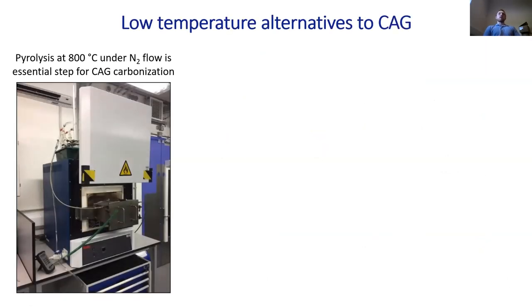The main drawback of the carbon aerogel fabrication route, which is still considered the state of the art for structural electrode materials, is that it involves a high temperature step, also used, for example, for fabricating carbon nanofibers presented by Servann. In this case, we can have some traces of water in our carbon aerogel precursor, which can cause some oxidation of carbon fibers and drop of the performance. Also, this high temperature step is industrially ineffective.